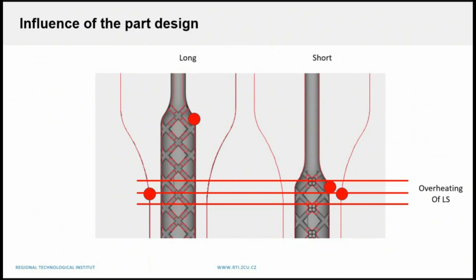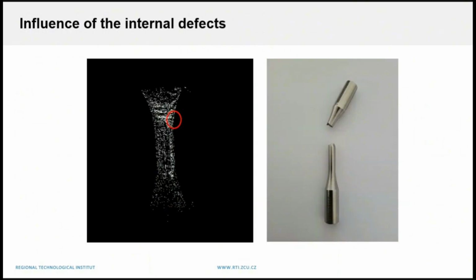And if we check the areas of the short systems, there is the maximum of the concentrators of cracks and defects. When we check, but not on this same part, but on different samples, here you could see all the white points are the potential defects, and here in this area, when the downskin starts, you could see that the amount of potential defects increases on the basis of the process. So this is a danger.